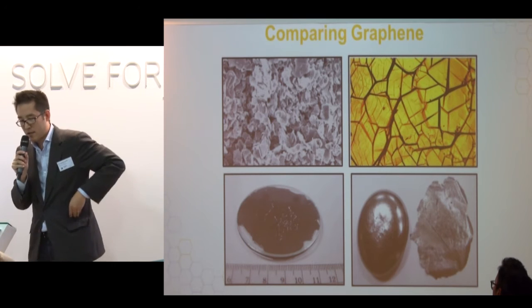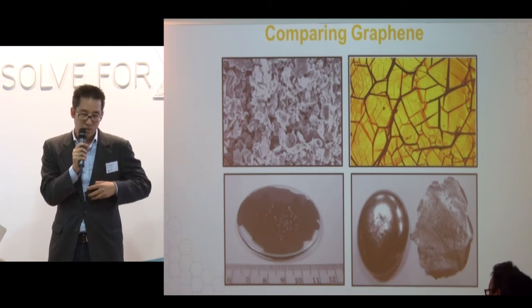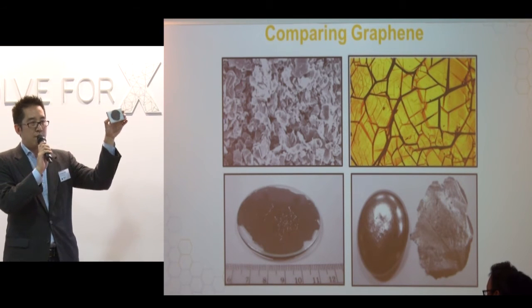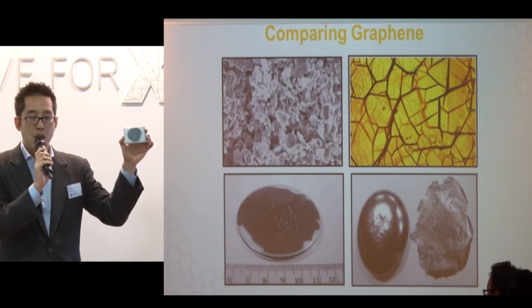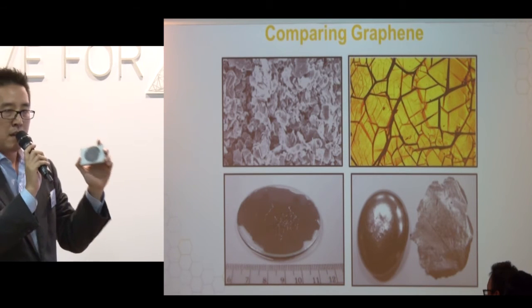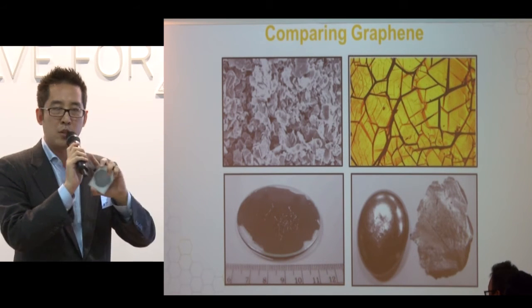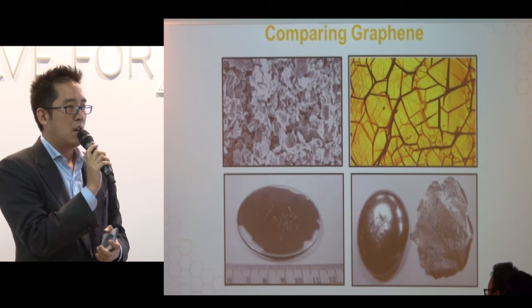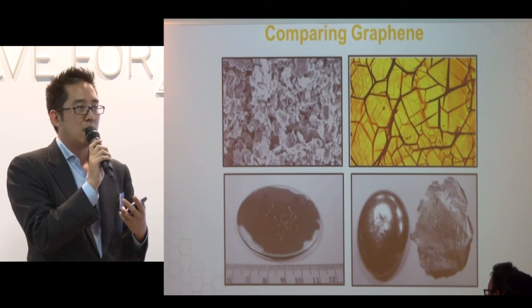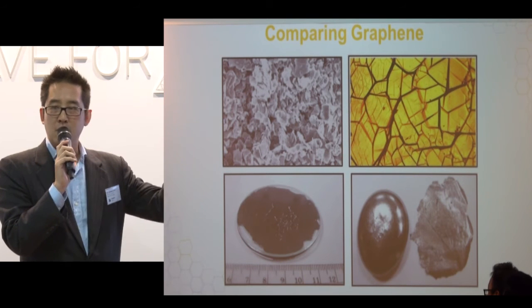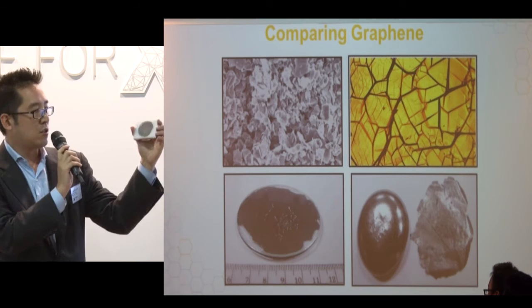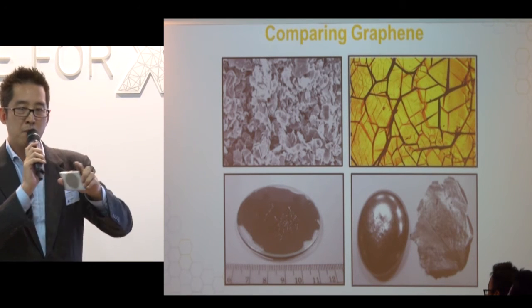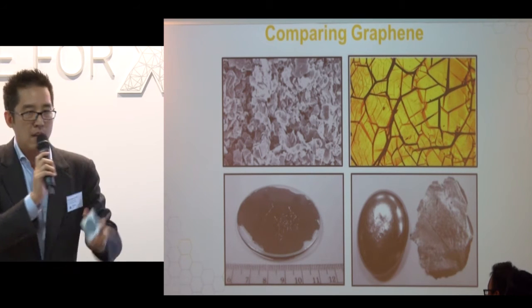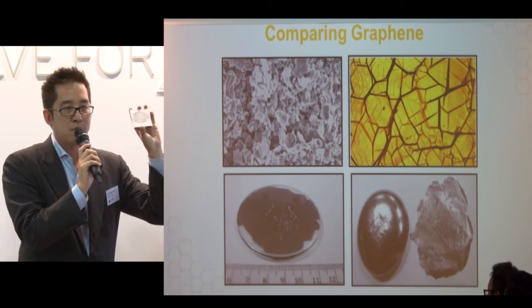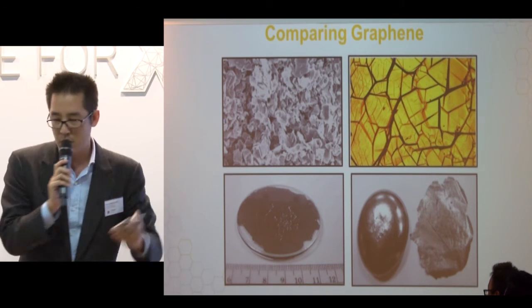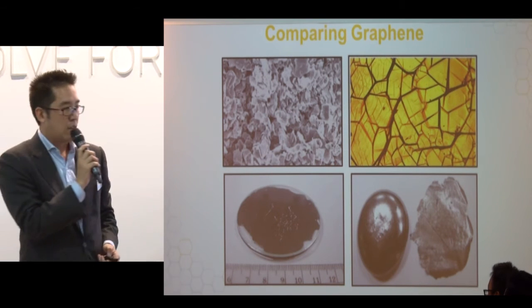And I'll show you right here in my pocket that we've been able to create this stuff. This is also a single sheet of graphene across a few centimeters of range. Most graphene has crystal domains, the areas of pure crystalline content, on the scale of nanometers to at most microns. We can do it across centimeters, and there's no limitation to this. This is because we use a small crucible. We can make it the size of a table if we wanted to. We demonstrated this in 2006, four years before the Nobel Prize was awarded. So I think we have a very good basis for doing this kind of stuff.